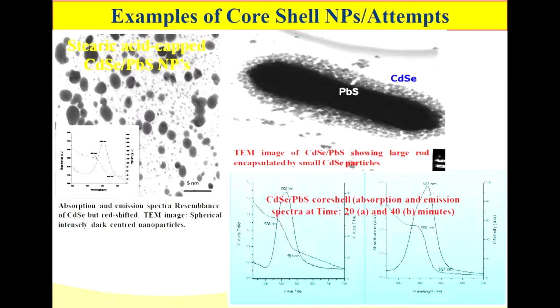you're adding cadmium selenide into lead sulfide, the contrary happens, such that at a lower time, you still get very nice, small, nicely sized distribution of particles. But as you increase the time, you start realizing that lead sulfide starts growing to be bigger and makes some kind of a rod-like structure with an assembly of CdSe on the surface thereof. And also the optical properties tell the same story, that indeed you've got a lot more CdSe dominating on both sides because of the fact that you've got cadmium selenide forming on the surface there.